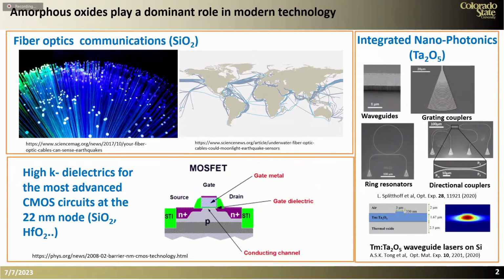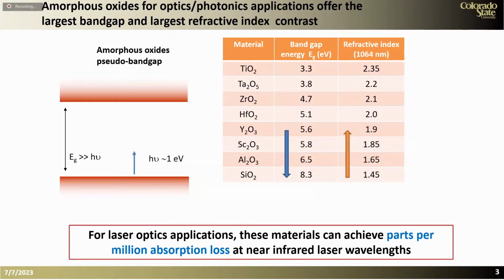Now you are all familiar that amorphous oxides are ubiquitous in many technologies, and one of them is fiber technologies. They are also used as high-K dielectrics in CMOS circuits, and in photonics they are used essentially to create index contrast to confine light. The reason why amorphous oxides are so attractive is because they offer a large bandgap and, in addition, a high index contrast, and this is exactly what allows us to confine light. And for laser optics applications, these materials can achieve parts per million absorption loss at near infrared wavelengths.